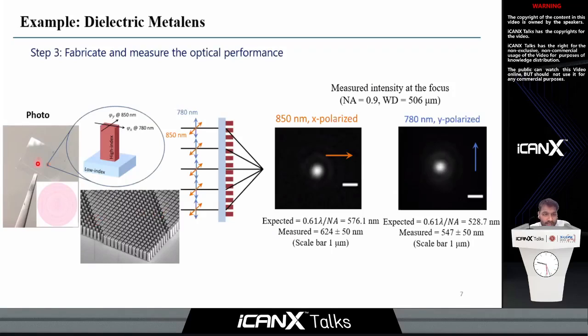Shown here in this optical image are two metasurfaces, 2 millimeters and 3 millimeters in diameter. They look basically like a pen mark on a glass slide, but really they are high numerical aperture, 0.9 numerical aperture metalenses. In this particular case, these metasurfaces are composed of rectangular nanopillars that are able to focus light at these two wavelengths, 780 and 850 nanometers, at the diffraction limit at a distance of approximately 500 microns. The reason for this choice of wavelengths was for a rubidium trapping application that I'll allude to in a second.